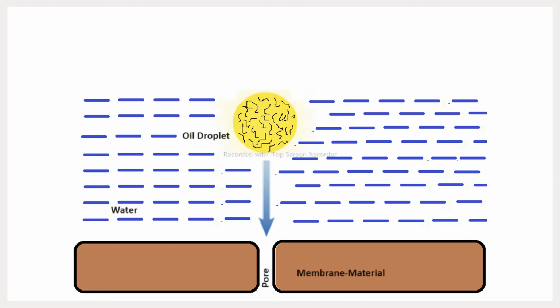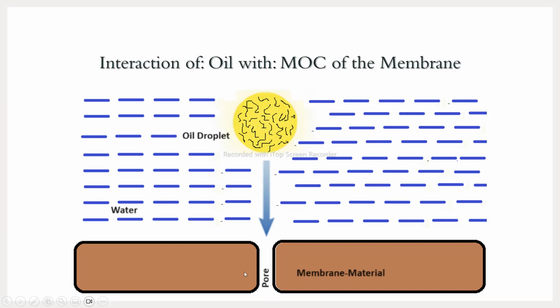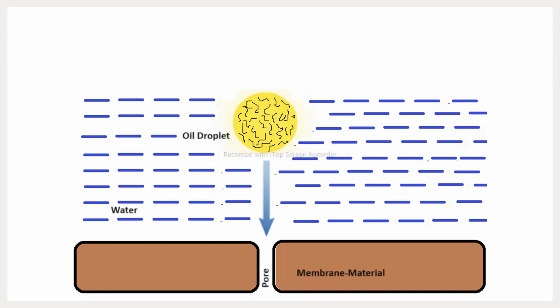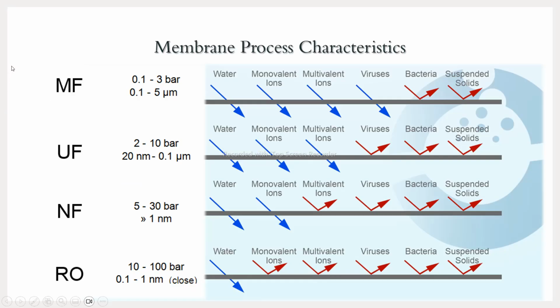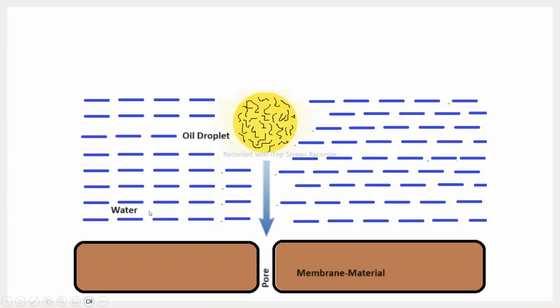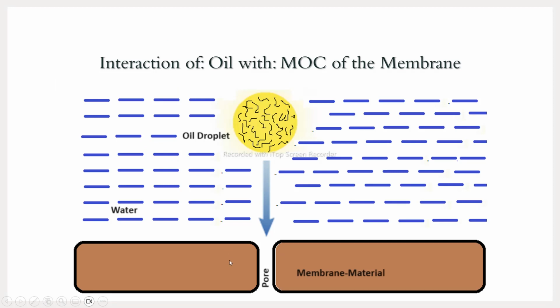But the interaction of oil molecules with the material of the membrane is important, because we generally use membranes that range from UF to NF for oil-water separation. So how does it separate oils? Actually, the membrane material is such that it repels the oil molecules and the oil droplet, and prevents it from breaking into further finer droplets. That's how it is able to separate the oil from the water.